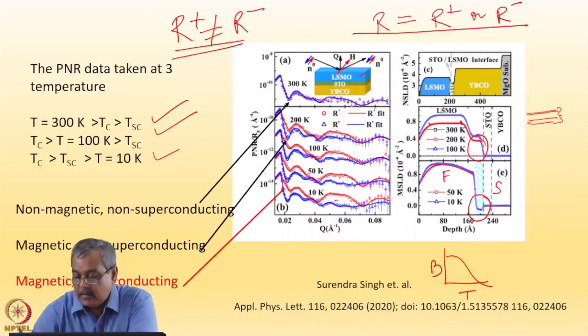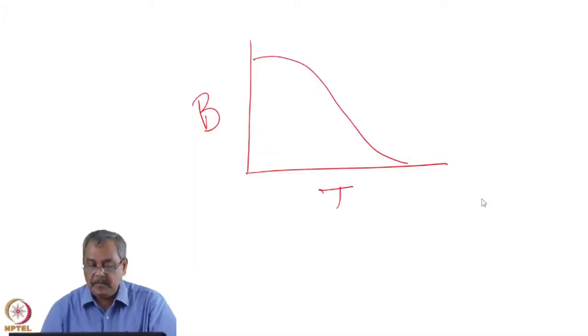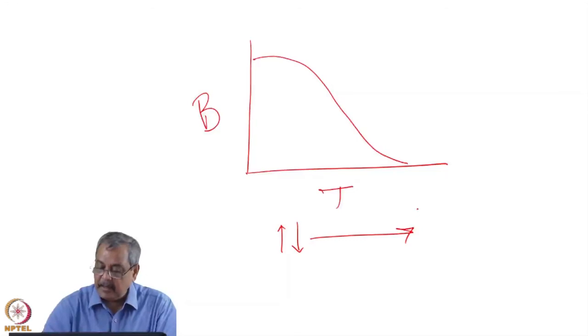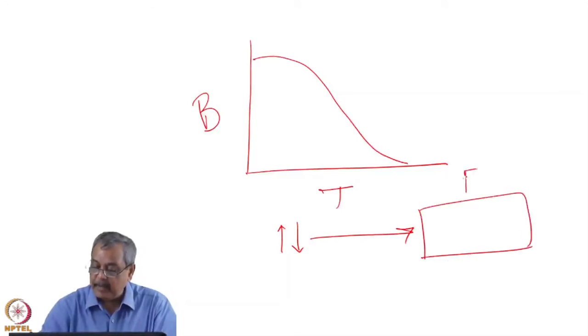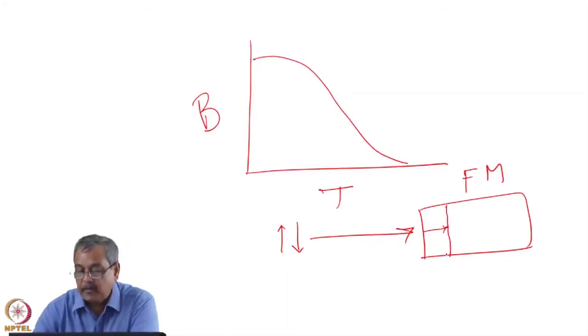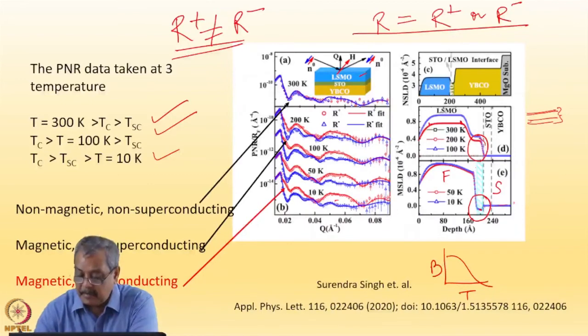Now this is something typical of Cooper pair tunneling. If the Cooper pairs, S equals zero Cooper pairs, enter a ferromagnet, then they will tend to cancel the magnetism in the ferromagnet, because that is the nature of superconductors. The penetration depth will dictate up to what distance it is partially or fully able to cancel out the magnetic moment density. And that's what we found in this experiment.